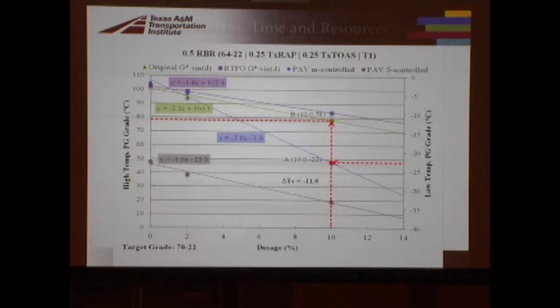And then we're going to check the high temperature grade, and the high temperature grade at that point is a 78. That's not a 70 minus 22, right? That's a 76. So we would do a second step where we'd continue down this line, adding in recycling agent until we bring it down such that it's a 70. So we need to get this number in half, I forgot to mention that, in 0.5% increments. So as a practicality measure, we're doing this in 0.5% increments. So we add it in until we at least get below a 76. So in this case, we get a 74.